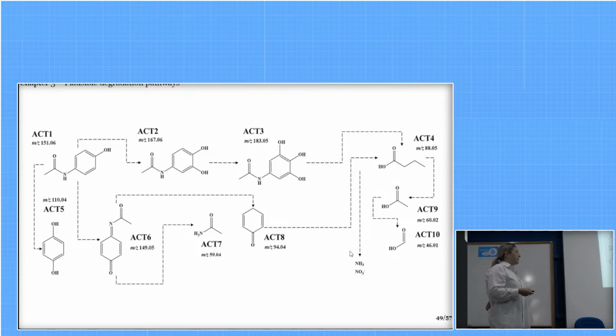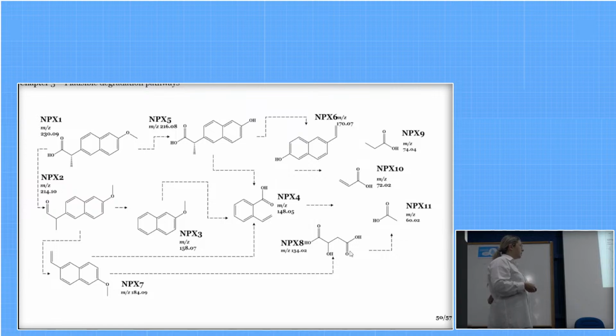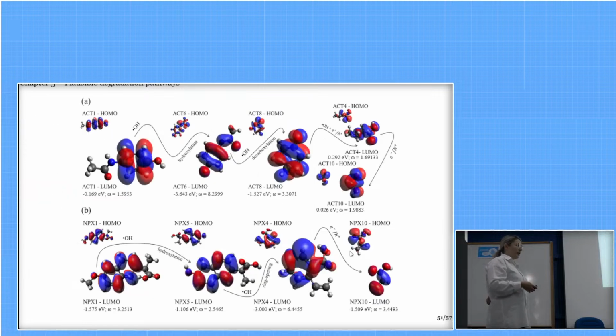We also investigated the plausible degradation pathways for acetaminophen and for naproxen, and we studied these using quantum chemical calculations. So we observed that for the most plausible routes, according to the values estimated for reactivity, the fragment ACT1, which is the pristine molecule for acetaminophen, suffered reactive oxygen species attacks, leading to its hydroxylation, a successful decarboxylation of the fragment, then the combination of reactive oxygen species and electron charge mobility for its mineralization.